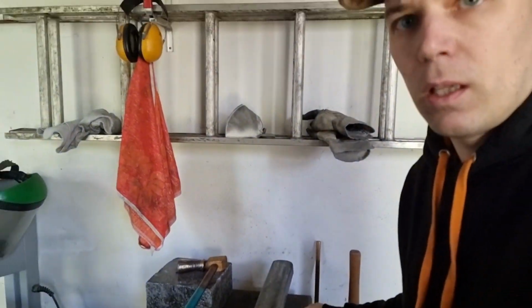And I think the penetration is about 1 millimeter per 24 hours at about 900 degrees Celsius, so you can do the math there. So if you have a thick material, then you just need to subject it to that temperature for a longer time. If you have a thin blade, then some hours may already do the trick in order to get a solid piece of steel.